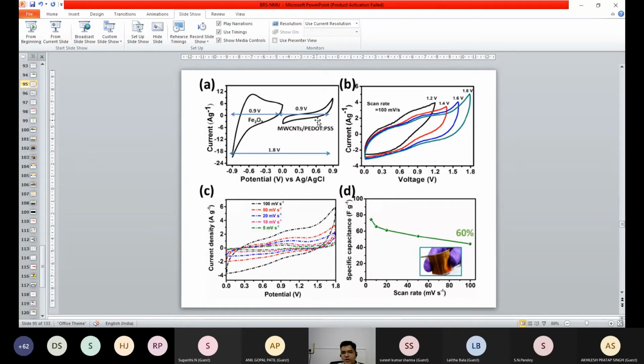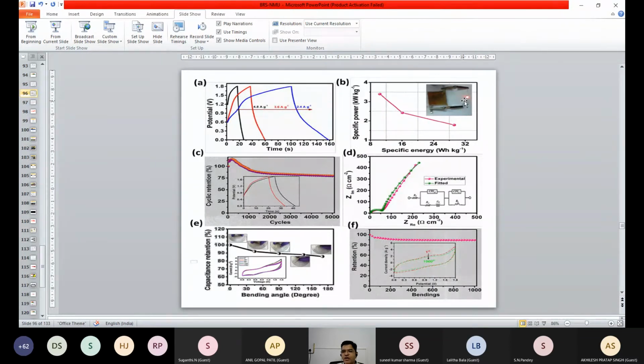So if you have one in the positive and one in the negative as an asymmetric device, it is possible to increase the voltage window up to 1.8, which is the addition of this one and this one. So we got a voltage window of 1.8 volt, right, by using the asymmetric mode. But here we observe that the drop in capacitance with respect to the scan rate is up to 60%, right, that we observed. Not only this, we also ran a small LED using this device. We have checked 1000 bendings as well, right? Bending means unbend, bend, like that. 1000 times we checked, and it is very, very stable.